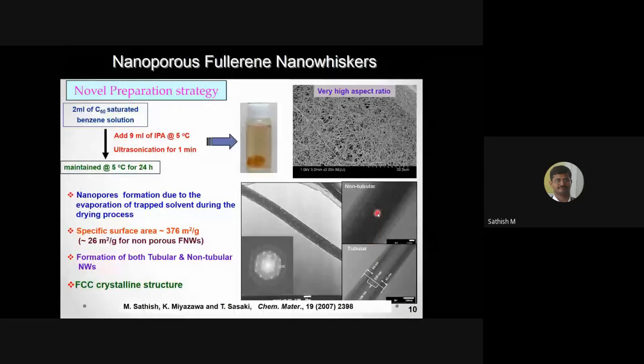Of course, you can selectively make non-tubular as well as tubular structures by changing the volume ratio. For example, here I added 2:9. Instead of 1:9, if you add this, the morphology will be the tubular structure. It may be tubular or non-tubular, but the size can also be controlled by changing the nature of the alcohol. Instead of isopropyl alcohol, if I use butanol, I get only rods instead of wires. The specific surface area of the material is 376 meters squared per gram.